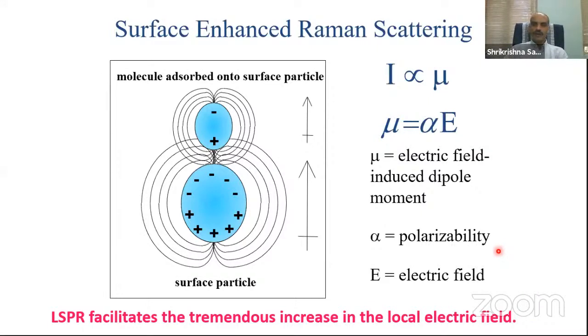Anyway, those Raman active modes are there. This polarizability is not in our hands, because it is decided by the molecule and how it is vibrating, whether it is symmetric or asymmetric. That's what we have seen. However, the electric field I can change, either by changing the intensity of my incident radiation. One way is to increase the intensity of my laser beam. However, if I increase it, it can damage my sample, especially biological samples or some polymers. So there is a limitation; I cannot increase the laser intensity beyond a certain limit. But because of these plasmonic nanoparticles, the electric field is getting enhanced, and therefore I am getting an increase in the intensity.